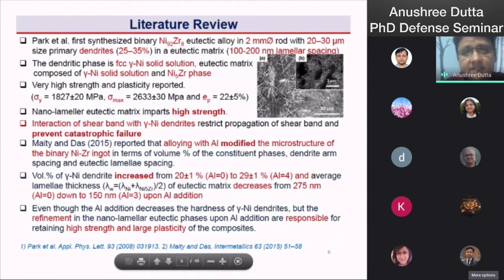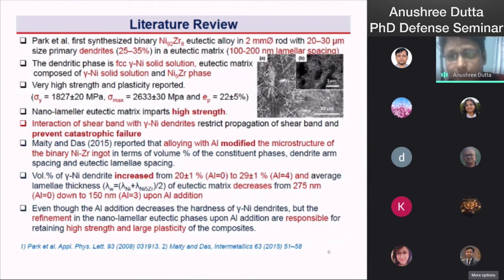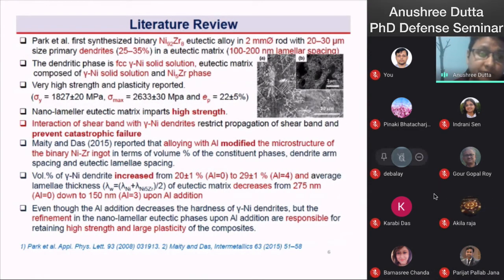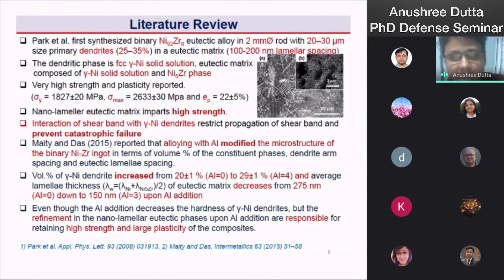Park et al. first synthesized nickel 92 zirconium 8 eutectic alloy in 2 mm diameter rods consisting of 20 to 30 micrometer size primary dendrites embedded in a eutectic matrix of 100 to 200 nanometer lamellar spacing. The microstructure of these alloys is comprised of an FCC gamma nickel solid solution dendritic phase embedded in a eutectic matrix of gamma nickel and Ni5Zr zeta phase.